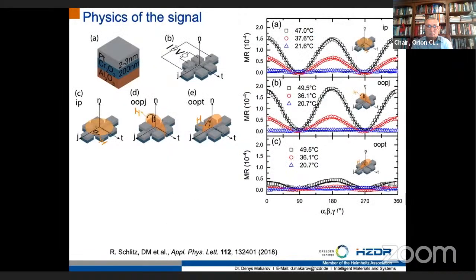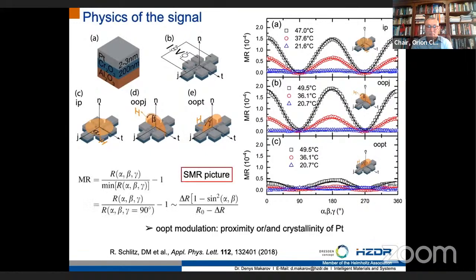In order to understand the physics of the measured signal, we collaborate with a group of Sebastian Gönnenwein at the University of Konstanz. As you can see, we pattern our sample in Hall bar geometries, which allows us to measure not only the transversal resistance but also magnetoresistance when the sample is exposed to magnetic fields which are rotated in three orthogonal planes, as is schematically shown here. By analyzing the angular dependence of magnetoresistance, we can identify the clear fingerprints of the spin Hall magnetoresistance.